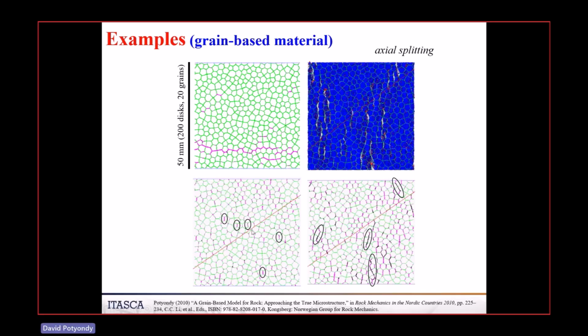If you look down here, forget about this line, it is irrelevant. If you look here, this is about halfway to the peak in a UCS test. And what you start seeing, and notice there's lots of partial damage along the grain boundaries, but you then also see these regions where the entire boundary is broken. That's what I've circled here. And then when you get near peak, again, these are all microtensile cracks. When you get near peak, what's triggering the failure here is you're getting these shear cracks, these black guys that are then going to end up linking up. These actually look a lot like wing cracks from a sliding crack.